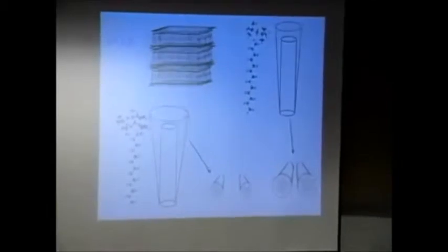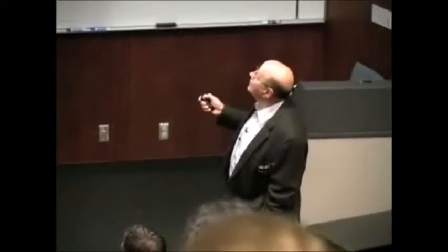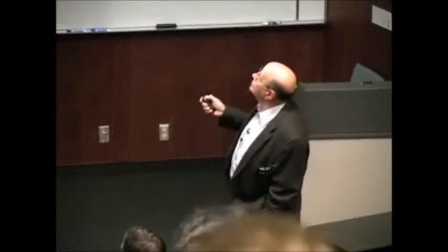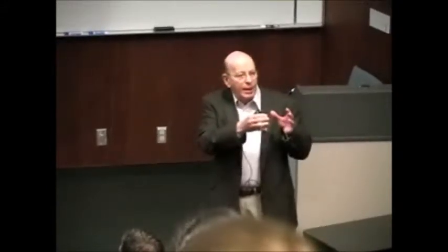What we came to realize is that when you hydrolyze the silica in aqueous solution, the next thing that happens is that the silica associates with the head group of the surfactant, and depending on the extent of polymerization of the silica, this one shows a dimer, this is a tetramer, I believe, those pre-oligomers of silica hydrogen bond to the head group, and so instead of the surfactant acting as a packing parameter of 1, it acts as a surfactant with a packing parameter less than 1.